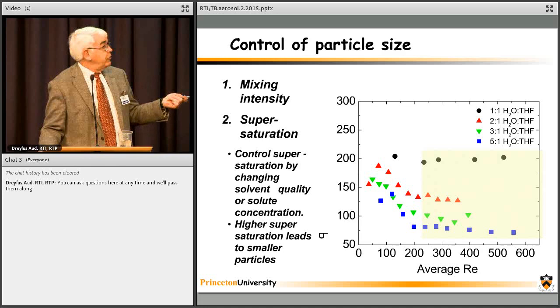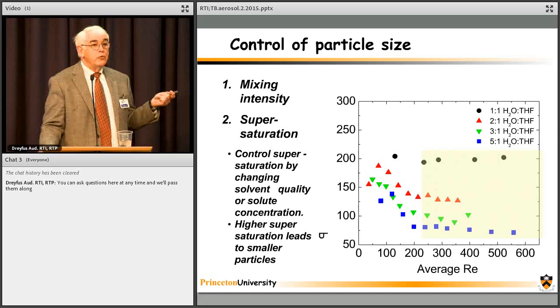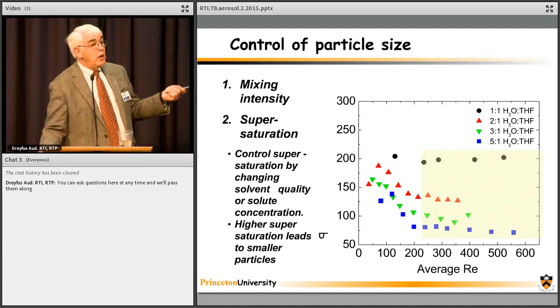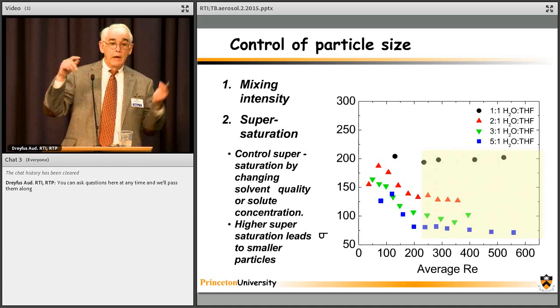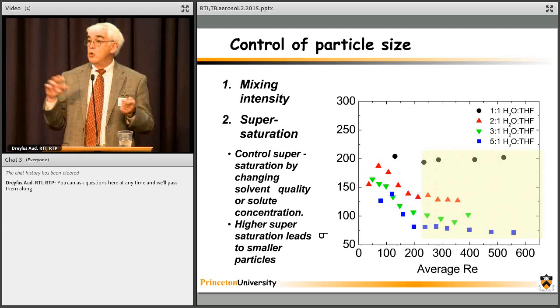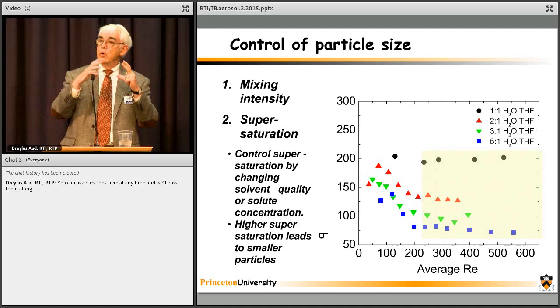So what we've done here is we've changed the solvent quality. Now in the topmost, the beta-carotene has the highest solubility. That means the supersaturation is lowest after micromixing, which means the nucleation rate is slower. Slower nucleation rate means you have fewer nuclei. And having fewer nuclei means that beta-carotene accumulates on those fewer nuclei, and so the average size is 200 nanometers.